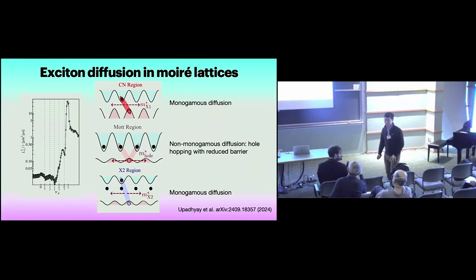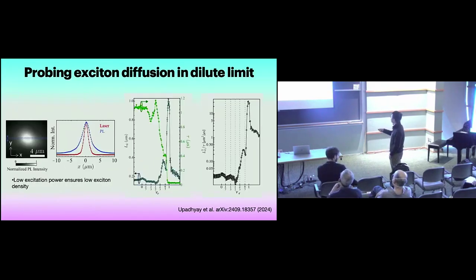Yeah. Could you show the lifetime? Oh, yeah. So this is the lifetime. The lifetime really is much shorter above mu equals 1, right? Yeah. So is this due to the fact that excitons now are spatially better overlapping in the transverse direction? I see. Because the same argument you make for the reduced barrier for electrons, the additional electrons will also see a weaker potential. Yeah, that's excellent. I think so. We didn't think about it, but that's a very good suggestion. Actually, we didn't understand this.